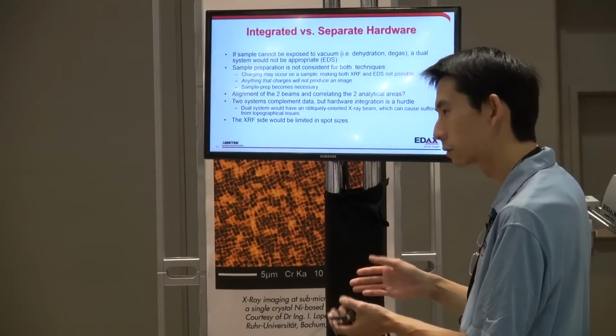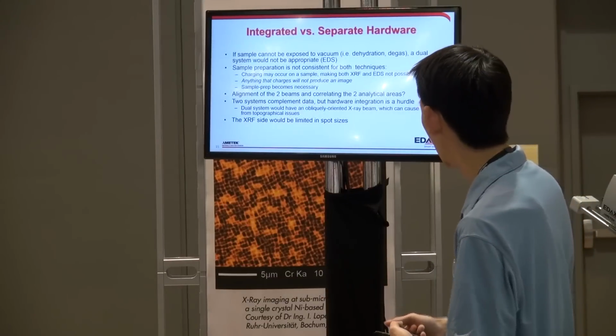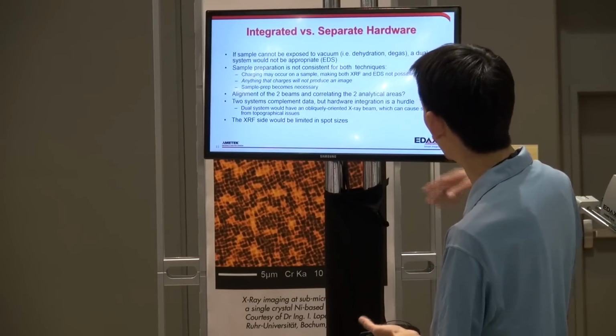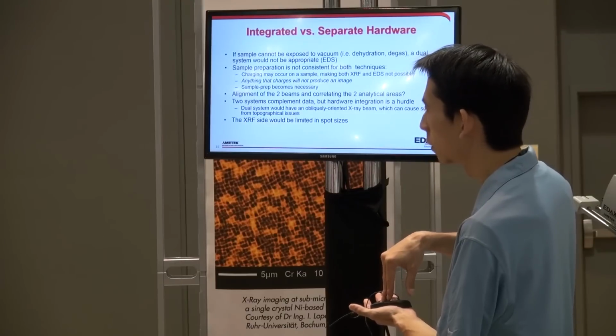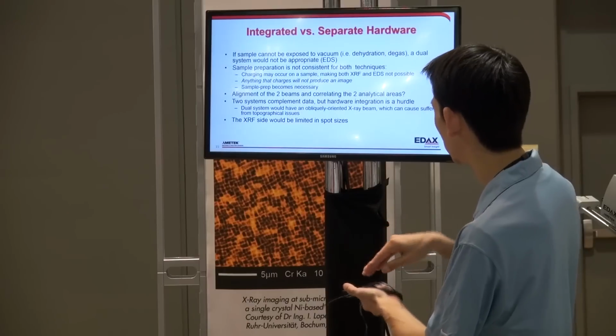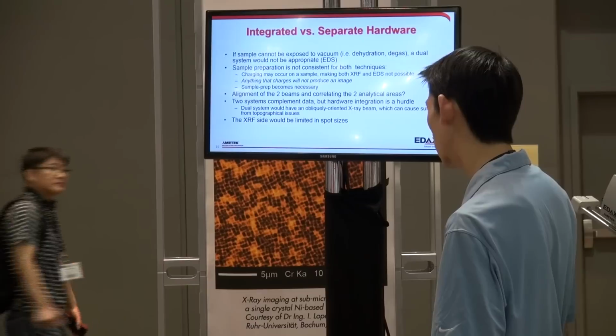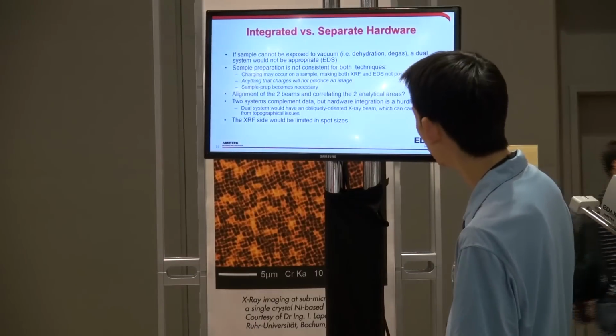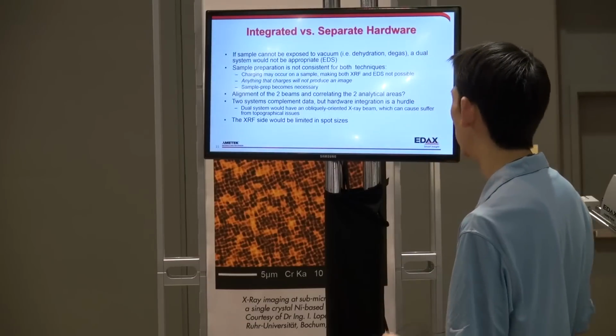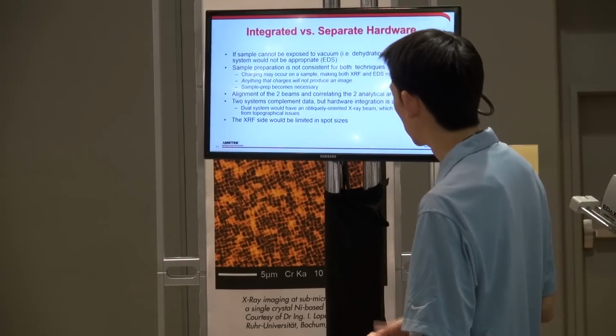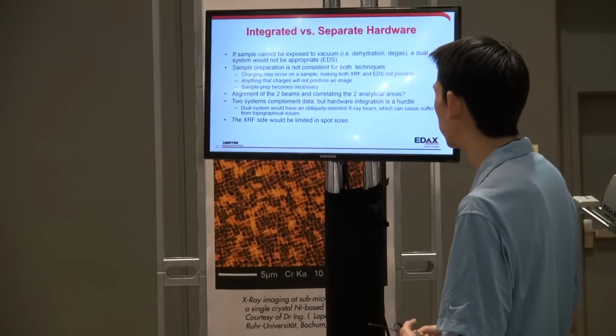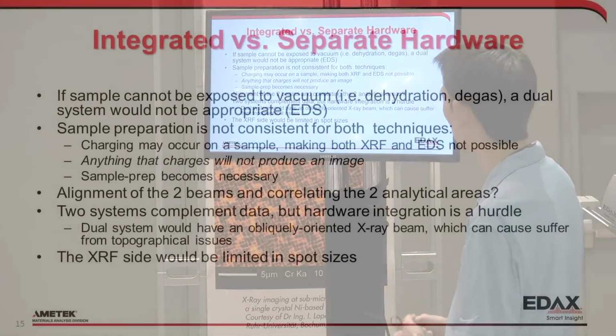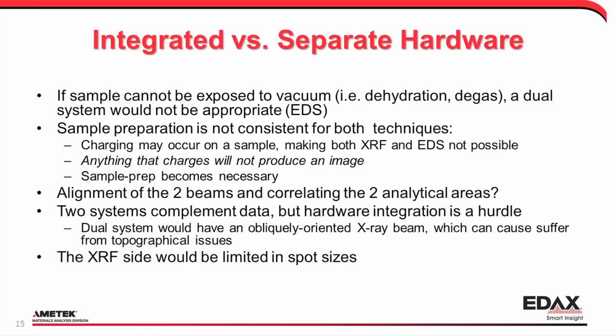The beam can elongate as you're coming in at an oblique angle, as opposed to a standalone unit where we have this beam coming in perpendicular to your sample, and the beam doesn't distort as you start coming in at an angle. Also, the XRF would be limited to one spot size probably, and we do have an option to select up to 3 different spot sizes. So presumably that capability would be lost if you integrated the two. So yeah, there's some hurdles to overcome on that side, both from the sample side and the hardware side, but definitely not out of the question.